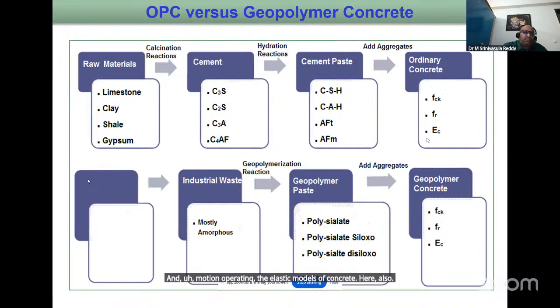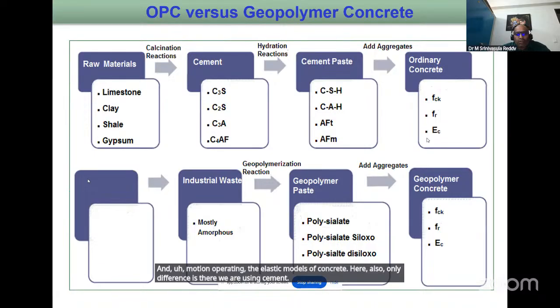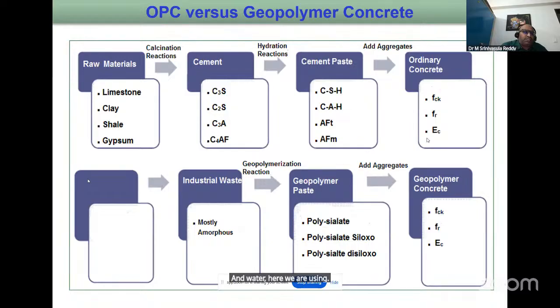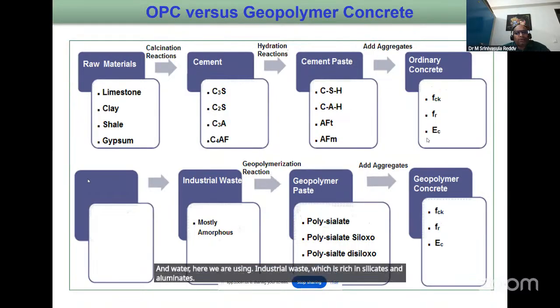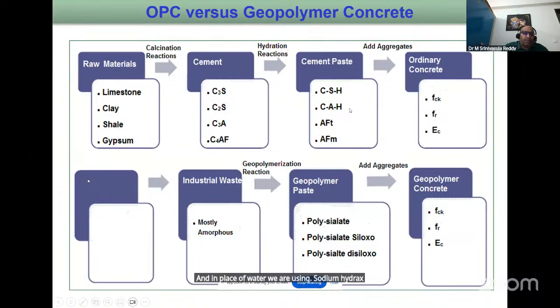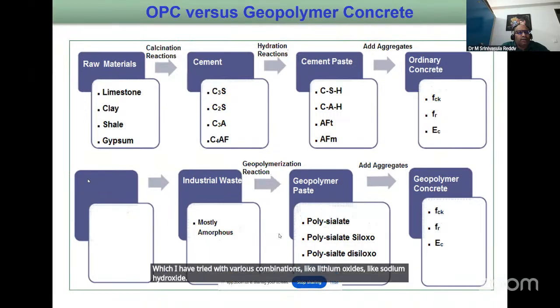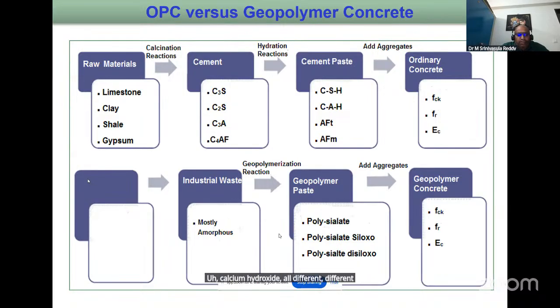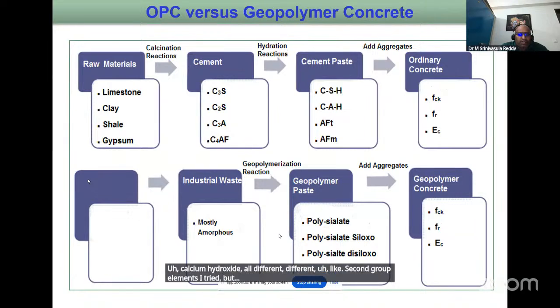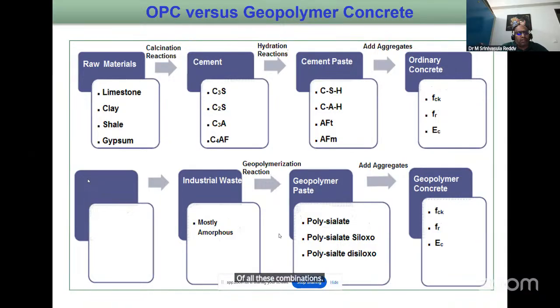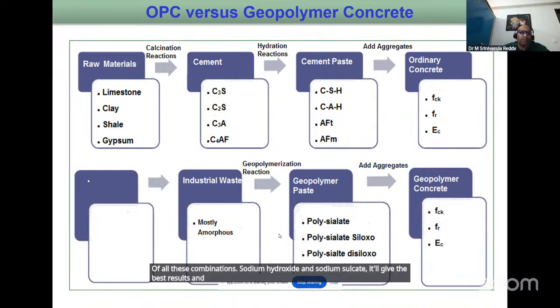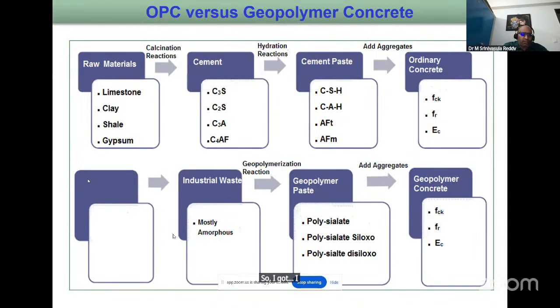Here also, the only difference is that there we are using cement and water. Here we are using industrial waste, which is rich in silicates and aluminates. And in place of water, we are using sodium hydroxide and sodium silicate. I have tried various combinations, like lithium oxide, sodium hydroxide, calcium hydroxide. So all different second group elements I tried, but finally what I found is that of all these combinations, sodium hydroxide and sodium silicate give the best results and best polymerization. So I did my further work using sodium hydroxide and sodium silicate, and finally I got a